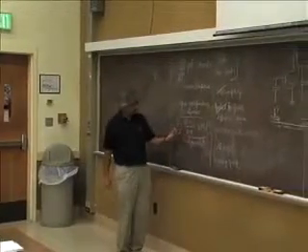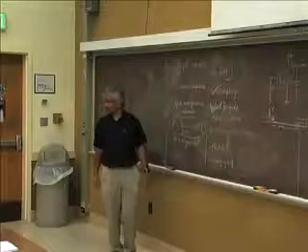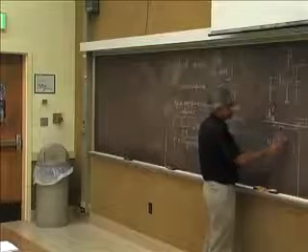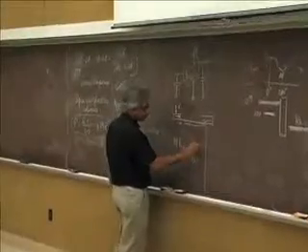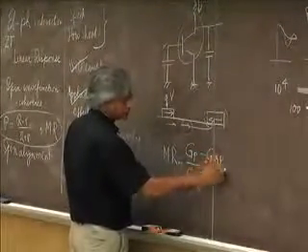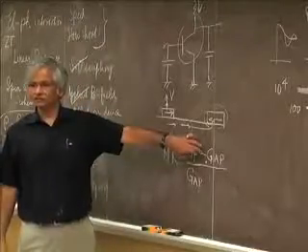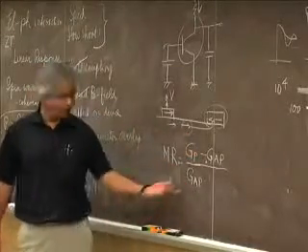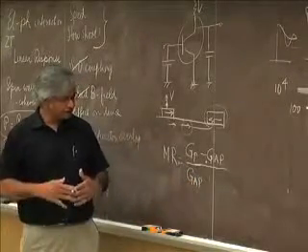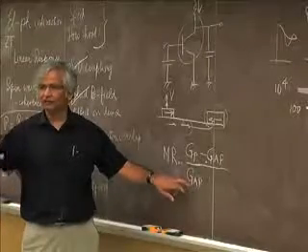About this polarization, I suppose this is a matter of choice to some extent, in the sense that you could have defined magnetoresistance in different ways. The way it is motivated, magnetoresistance is parallel conductance over anti-parallel conductance minus 1. So you look at how much the conductance changes and divide it by the anti-parallel conductance. Now, why anti-parallel? You could have used parallel, for example. But when you do anti-parallel, then in the best of situations, the denominator could be 0.